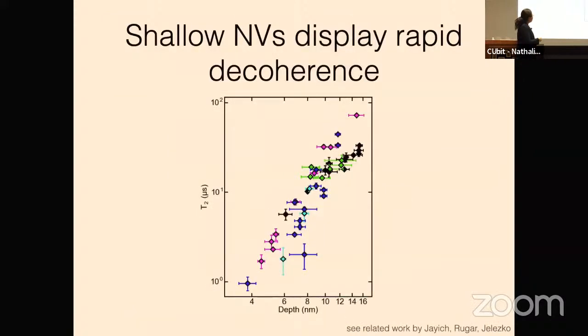So one of the ways that we know that this is a big problem is that if you just look at NV centers and map out their coherence time as a function of depth away from the surface, you see this horrible power law scaling as you approach the surface. I wouldn't take this scaling too seriously, but it's something like 1/r⁴. So while we have these coherence times of milliseconds when you're in the bulk, you get to within, let's say, 100 nanometers of the surface and you see this terrible crash. And when you're within a few nanometers of the surface, it's more like less than a microsecond.